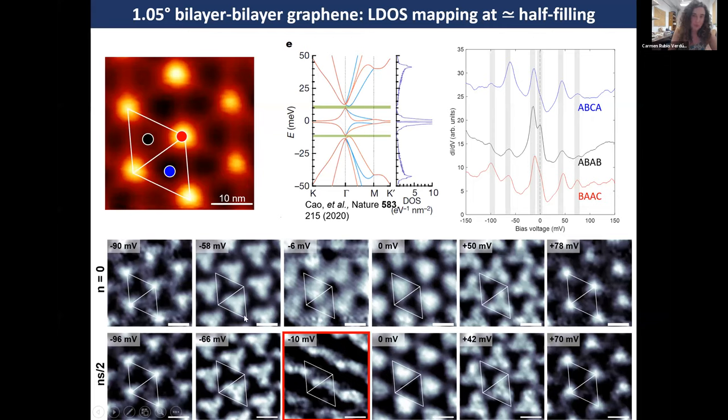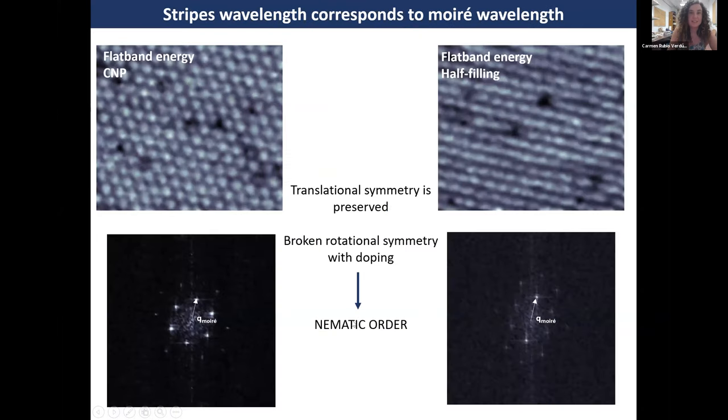So I've showed you this for small regions, but I showed you at the beginning that we have these very big regions of uniform Moire, right? So let's see what happens. Here is a 200 by 200 nanometers map. So you can see the brightest spots of the Moire for charge neutrality at the energy of the flat band. Now, when we do the very same thing, but at the half-filling condition, so we dope the system, you can see that it develops these stripes that I showed you before. They are long range